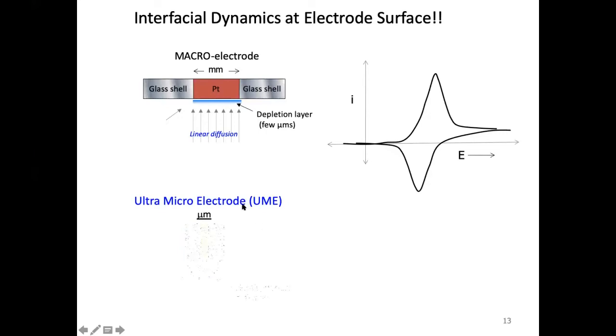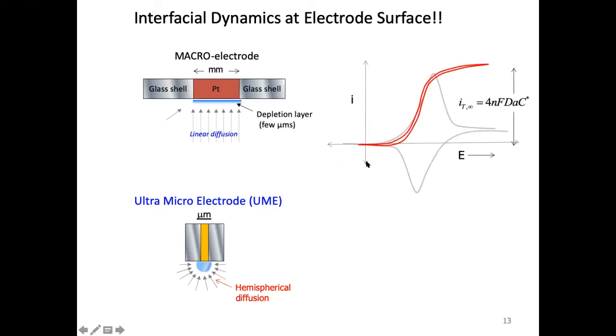Now instead of linear diffusion, I am going to have hemispherical or spherical diffusion. This is three-dimensional diffusion, whereas that was one-dimensional diffusion. This is faster. And if you see the current response on an ultramicroelectrode, you will get a response like this, an S-shaped response, like we typically used to see in polarography. Remember this, in polarography we used to get an S-shaped response.